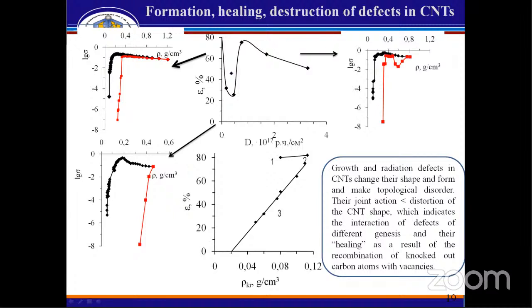Multi-layer carbon nanotubes 18 nanometers in diameter were irradiated with gamma quanta with a dose up to 3.3 times 10^17 gamma quanta per centimeter squared. After exposure to radiation, the electrical conductivity curve changes. It grows less gradually due to the change in the structure of CNT and the appearance of defects at the stage of unloading, and a notable change in the shape of the electrical conductivity curves is obtained in comparison with the situation before irradiation. For unirradiated CNT, the elastic limit is 18%. After gamma quantum radiation, a minimum is observed on the dependence of the elastic limit on the radiation dose. This indicates the formation of defects at low doses of gamma radiation.